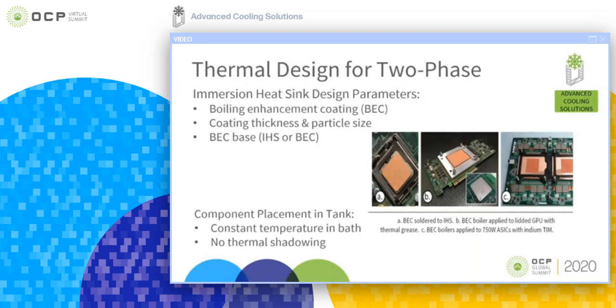So direct submersion of a bare die or lidded package is not an optimal way to do two-phase immersion. So for passive pool boiling heat transfer, you need the boiling enhancement coating on the IHS or integrated heat spreader, or a heat spreader which will work as a heat sink on the top of the lidded package. So there can be multiple ways, various techniques can be used to enhance boiling heat transfer, and that is called boiling enhancement coating, which increases the surface area on the top of the boiler. So there are various techniques, right? So it can be extended surfaces like metallic or graphite fins or foams or porous organic coatings. And the most common way of doing this is porous metallic coating, where you can use the copper particles fused with silver. And you can either use different techniques like plating or sintering or brazing on the top of the heat spreader and make the boiler.